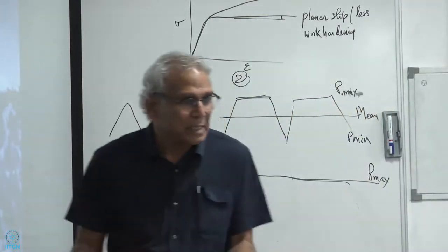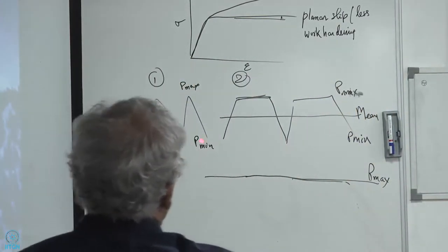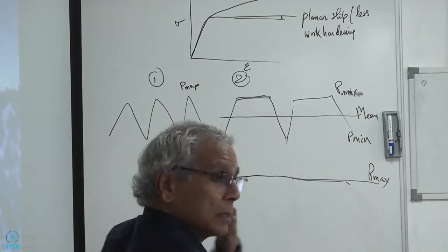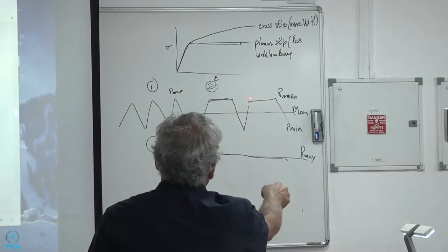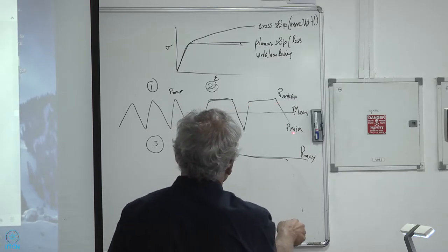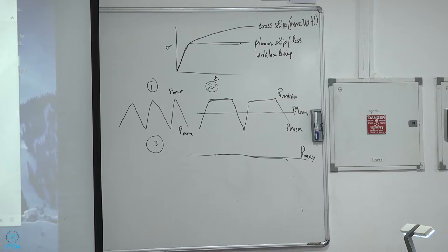So, unusual, okay, so this is the data. First, let's look at the data. Stress is about 80% of the yield stress. Okay, it's below the yield stress, 80%. Titanium 6211, colony, and 6211 basket weave. So these are alpha-beta processed, these two alloys, the colony and the basket weave, and then titanium 5, 2.5. Okay. Look at these strains. 1, 2, 3, 4.2%.